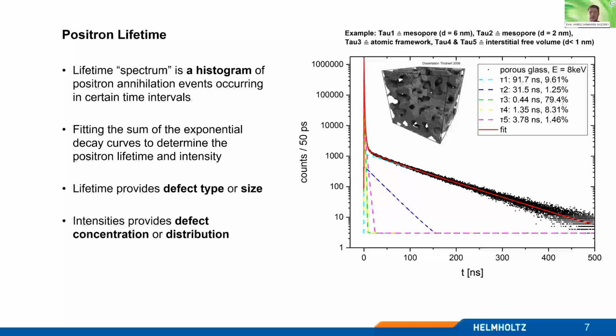So as you can see here, to fit this histogram or this positron lifetime spectrum properly, you need 5 exponential decay curves, each with an individual lifetime and intensity. And as you see, the tau 1 is referred to the mesopore of the porous glass, which means you have 91 nanoseconds, and this can be translated into up to 6 nanometer pore size, and also a second pore within the porous structure, which is then 31 nanoseconds, and this is then up to 2 nanometers, and so on, up to the atomic framework of the glass, and also some interstitial free volume, which is lower than 1 nanometer. So you can investigate a broad field of material properties if they are correlated somehow with the defect structure or the porous structure of your material itself.